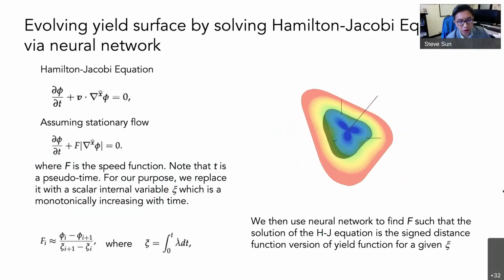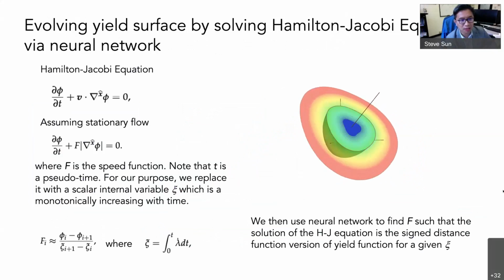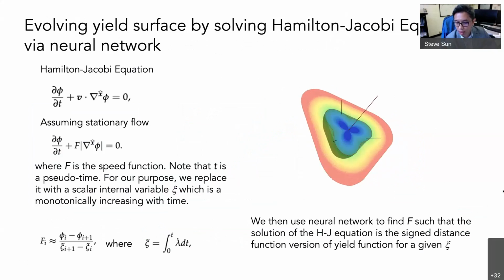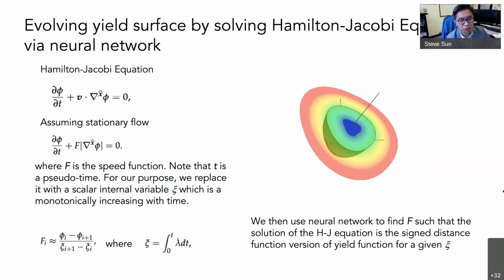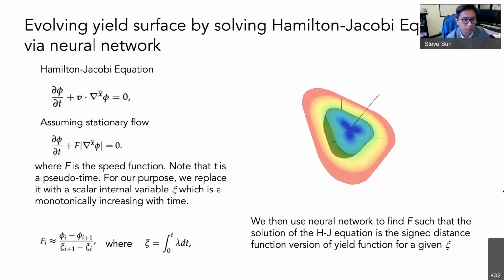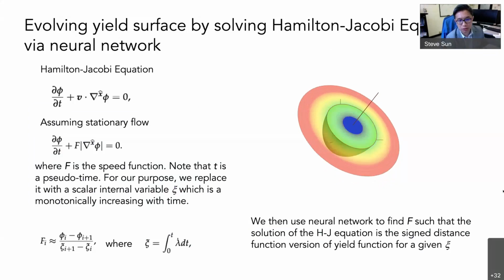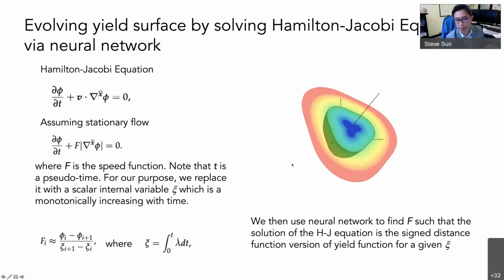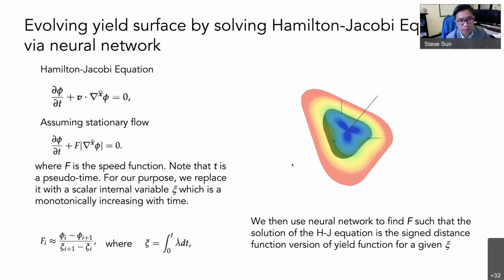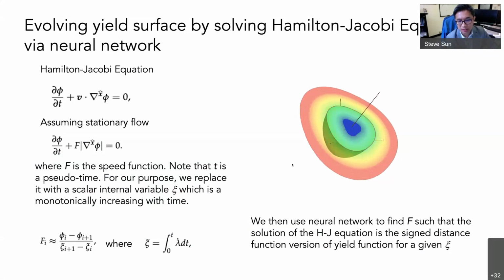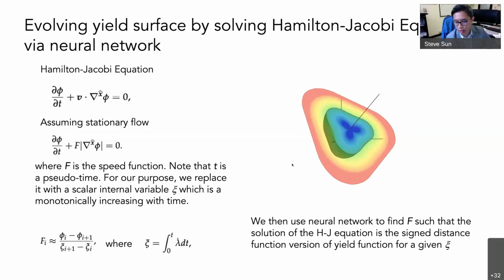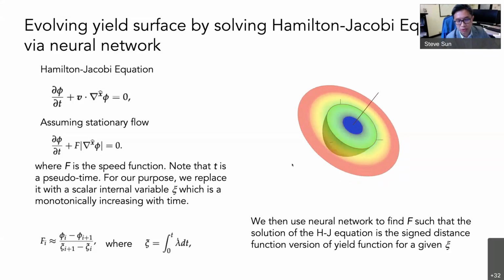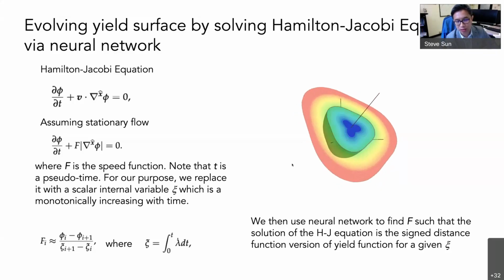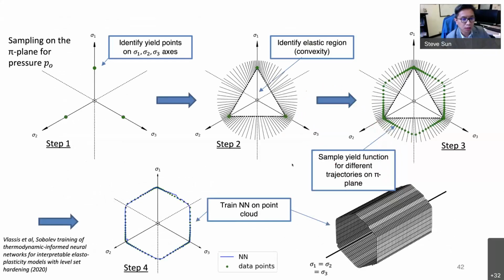In this case, we formulate the yield surface evolution as a Hamilton-Jacobi equation. You can think about this as very similar to training a PINN problem, where we try to solve that Hamilton-Jacobi problem with the yield surface corresponding to the principal stress and the accumulative plastic strain. The only difference here is that we only need to train this PINN problem once, and then the result would be a constitutive law that can be reused many times as a replacement of the classical return mapping constitutive law.